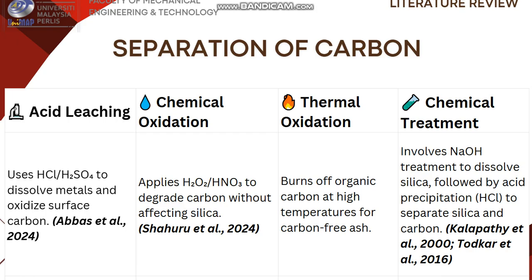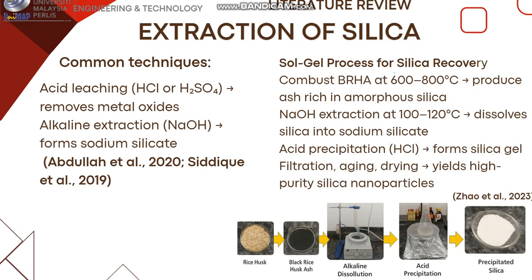Here are the various techniques used for carbon removal: acid leaching, chemical oxidation, thermal oxidation, and chemical treatment. For the extraction of silica, the general steps include combustion to obtain silica-rich ash, treating it with sodium hydroxide to form sodium silicate, precipitating with hydrochloric acid to form the silica gel, filtering, aging, and drying to obtain amorphous silica nanoparticles. This process ensures high purity and low energy consumption.